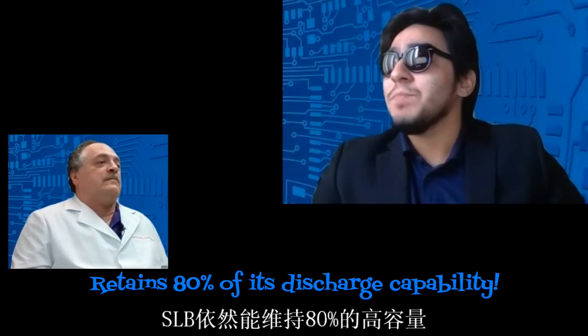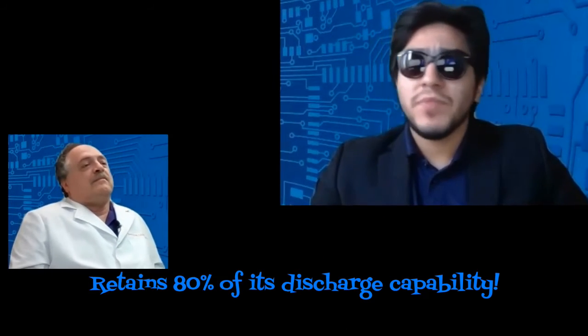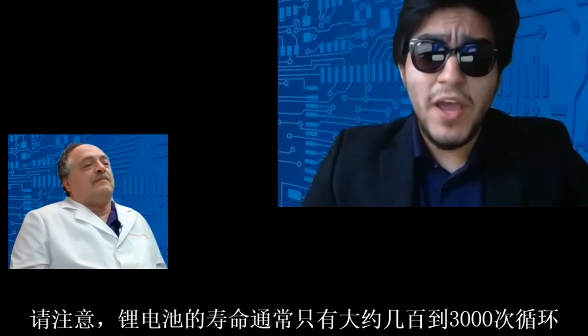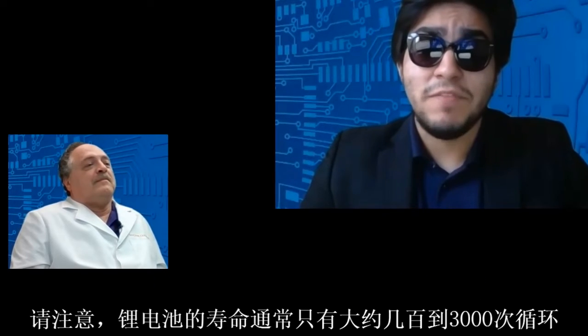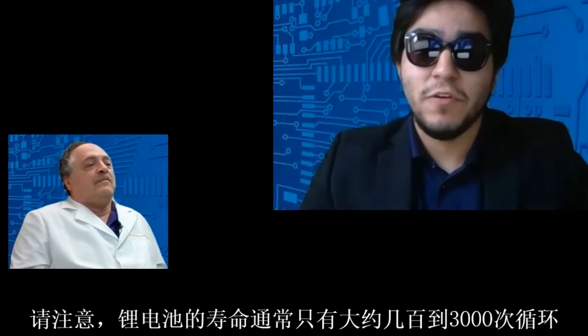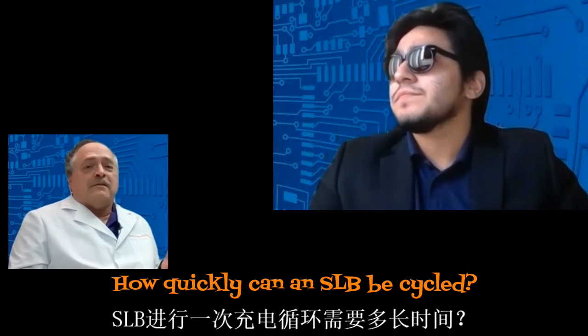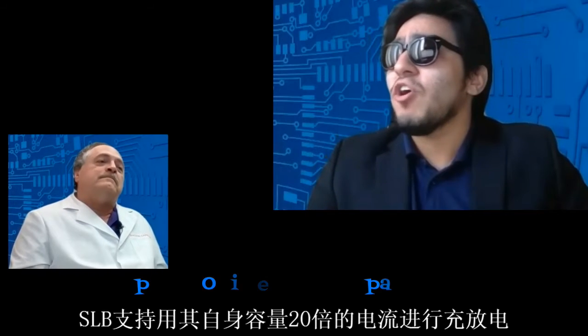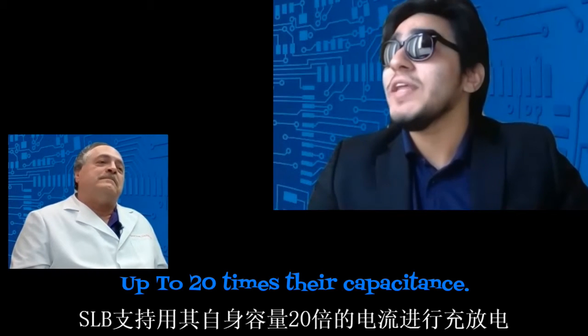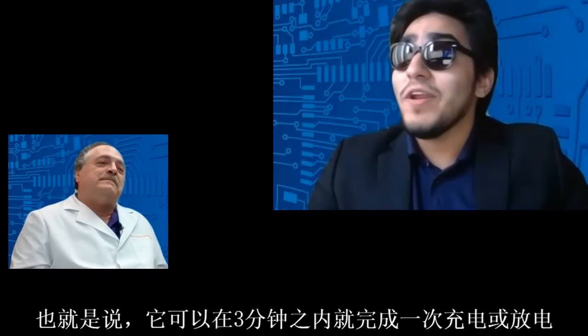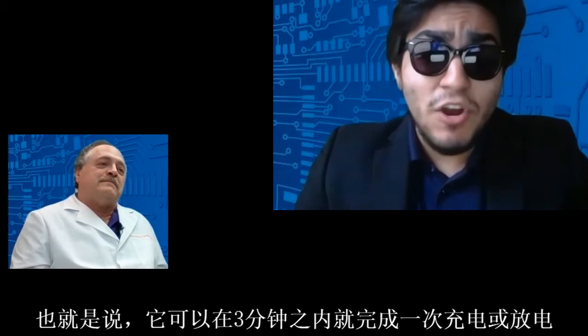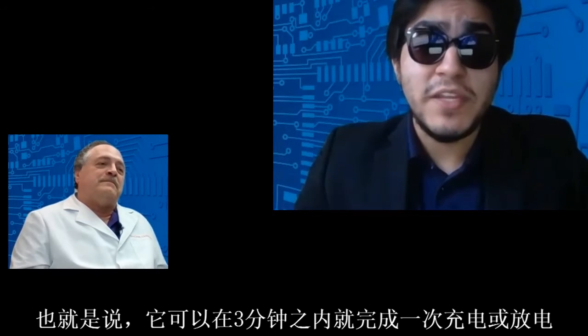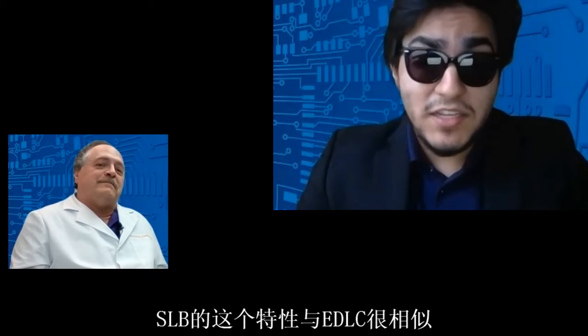After 20,000 cycles, the SLB will retain 80% of its discharge capability. Please note, a lithium-ion battery can only withstand a couple of hundred to 3,000 cycles before failing. How quickly can an SLB be cycled? The SLB can be charged or discharged at rates up to 20 times their capacities, or in other words, they can be discharged or charged in as few as 3 minutes. This is very similar to EDLCs.